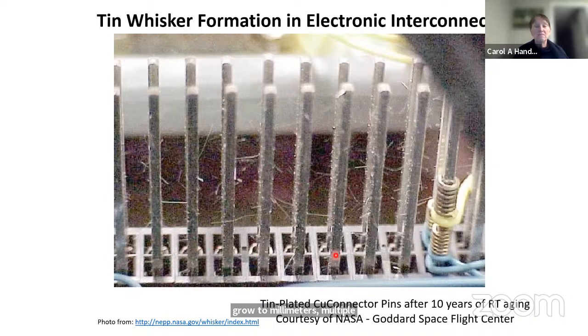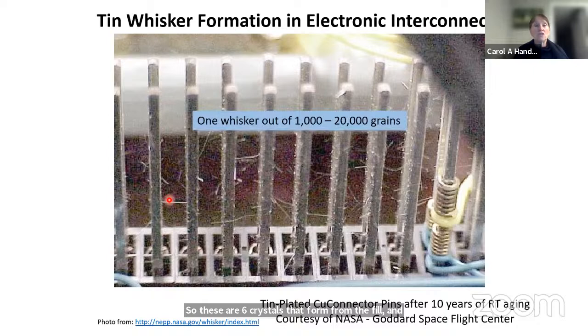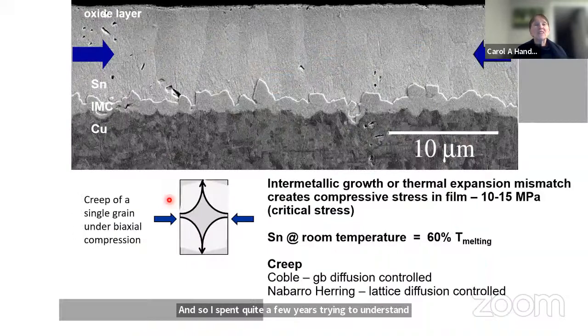This is a set of connectors. So these are probably, I'd say, 5 or 6 millimeters apart. So these are single crystals that form from the film, and these are forming because they relax the compressive stress in the film. So it can be typically one whisker out of 1,000 to 20,000 grains. So again, this is a relatively rare phenomenon. And so I've spent quite a few years trying to understand what made those particular grains form whiskers. So here's a scenario.